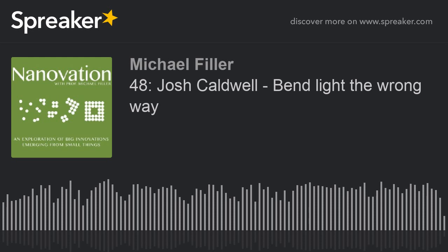But at that point, and even to this point, basic exfoliation is still pretty widely used. One of the challenges at that time was trying to get large area graphene, and epitaxial graphene grown on silicon carbide by a sublimation process was a nice way of potentially getting these large area films. So we were able to demonstrate you could transfer that off. We transferred it to a number of different materials, from silicon dioxide and sapphire, things with lots of dangling bonds, things with not so many. And then we filed a patent on this. I can't discuss potential licensing opportunities, but there had been some.